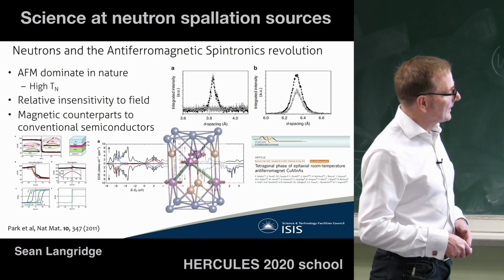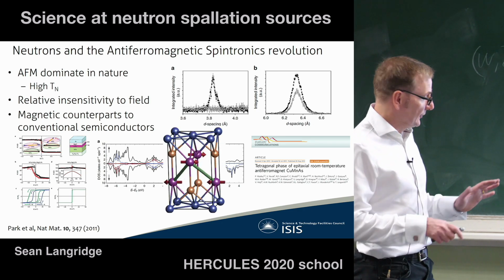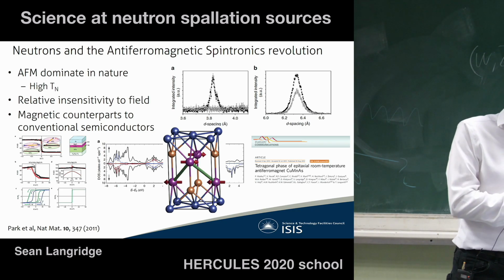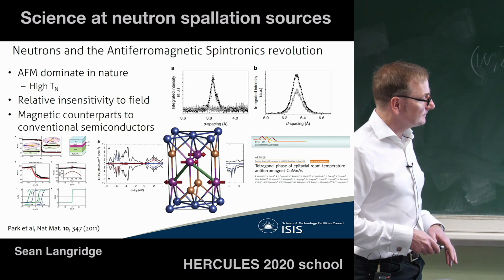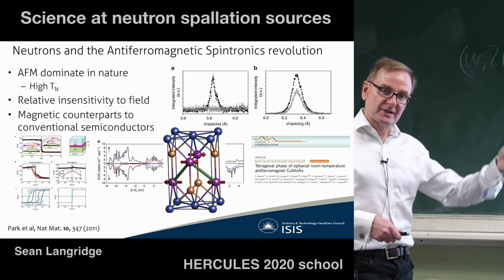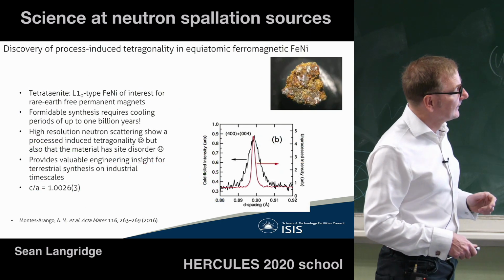By measuring various Bragg peaks, you're able to solve the structure that you could not do by any other technique. Okay? And that's a combination of high flux, good resolution, low backgrounds. That's what you get on a spallation source.